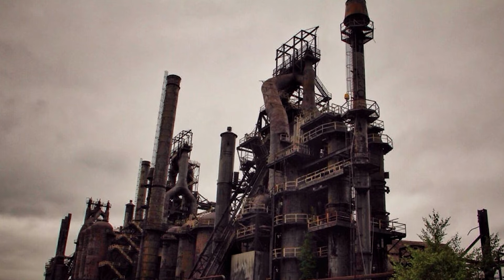Quenching involved heating the plate to 1,625 degrees, well above the critical temperature where steel's crystal structure transformed from body-centered cubic to face-centered cubic. At this temperature, the iron could dissolve significantly more carbon, and the alloying elements distributed uniformly throughout the matrix. The plate had to be heated uniformly. Cold spots created differential crystal structure that became failure points under ballistic impact. Heating a 2-inch thick plate uniformly required hours in precisely controlled furnaces. Once the plate reached temperature and soaked long enough for the center to equilibrate with the surface, it was removed and immediately plunged into a quenching medium.